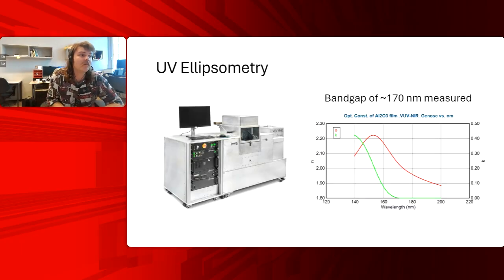The UV band gap, actually, we've measured down to 170 nanometers. So we still expect some losses as you get down to 260 nanometers, which I'll show you guys as already 4 dB per centimeter. But theoretically, the band gap of our material is very, very high, with a band gap of 170 nanometers being measured by a UV Woollam VASE.